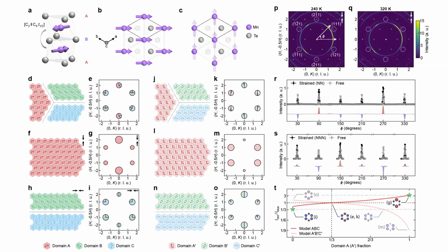Actually, we have those data. So far the temperature dependence is mostly done at low temperature, right? Once we do the strain measurement, we typically cool to a particular temperature and then sweep the strain. What you're saying is whether we should do it as a whole temperature series. We actually have those data. We can take a look.